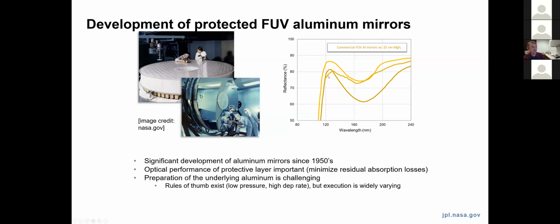In order to make a mirror coating, you essentially have to avoid that oxidation by depositing a protective coating on top. The one that has been the most popular choice over many decades has been protective coatings of magnesium fluoride. What I'm showing here is that even though these mirror coatings have been developed over many decades, there's still a lot of challenges in understanding the preparation of both the aluminum and the protective coating. And there's still an evolution to these processes that are resulting in improved performance depending on the material. And so even in modern examples, whether it's commercial vendors or other research reports, you can get a pretty wide variation in performance for notionally the same exact optical coating. And so this is another area where we thought ALD might be able to help out, is improving the consistency and reliability of the protective coating itself.